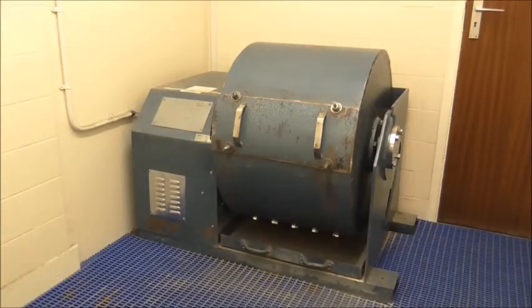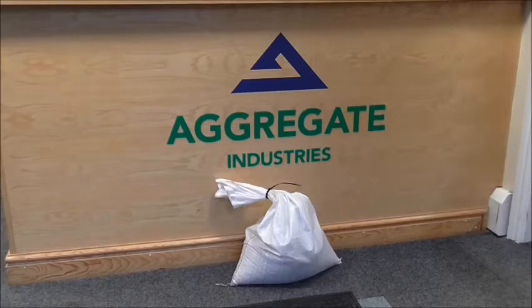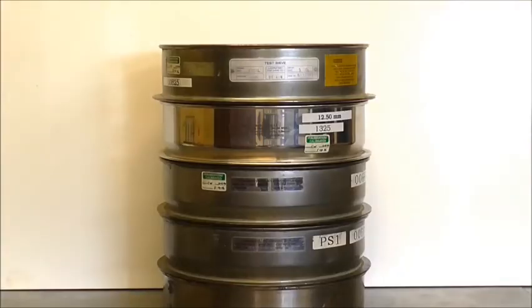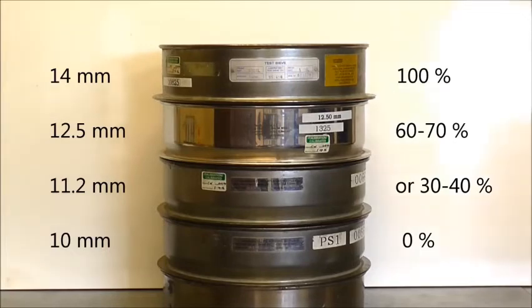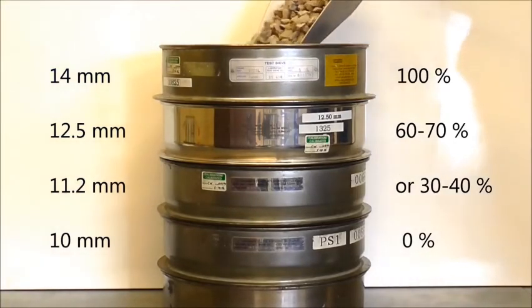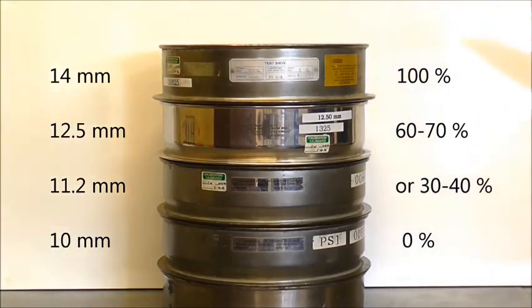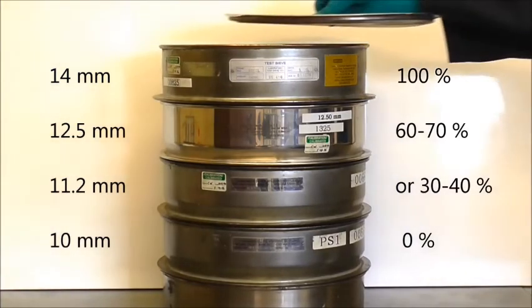Now let's take a look at the test in more detail, starting with sample preparation. The sample sent for testing must contain at least 15 kg in the 10 to 14 mm size range. Only material passing a 14 and retained on a 10 mm sieve is used. In addition to this, either 60 to 70% of this material must pass a 12.5 mm sieve or 30 to 40% must pass an 11.2 mm sieve. The sample must be reduced to create two size fractions by using just one of the intermediate sieves.